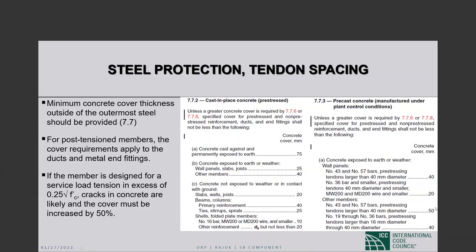There are ways to avoid these by using additional protection on the structure. So I've been experimenting with carbon fiber wrap for a while now. By putting those layers on concrete, the carbon fiber laminate does not only give you strength increase, it also gives you durability increase. I've shown through my previous research that the cover can be reduced by half if you use CFRP protection laminate on top of the structure. Now, CFRP laminate is a separate issue. It's used both in buildings and bridges in the US.